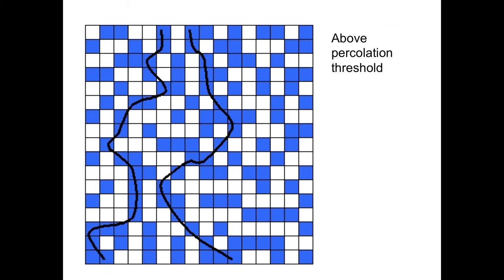Now why is this? Well, supposing the blue here is retained austenite and the white is bainitic ferrite. When the retained austenite content is sufficiently high, it percolates completely through the mixture of ferrite and austenite. So we are basically stressing the bainitic ferrite and the retained austenite.